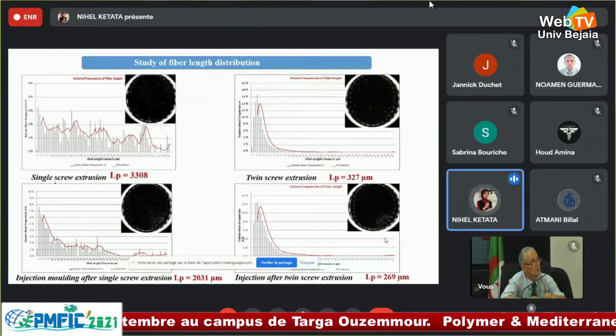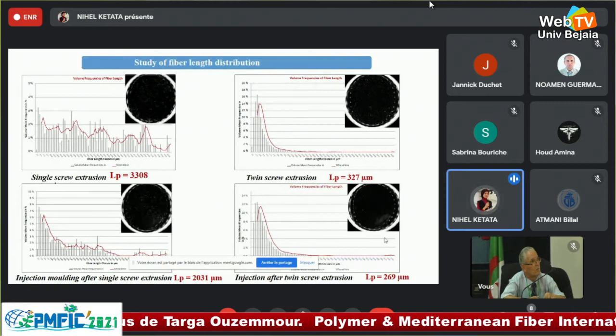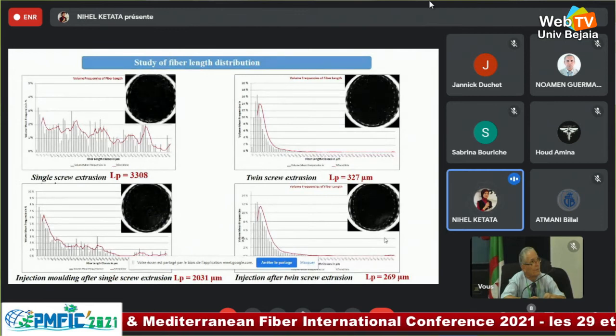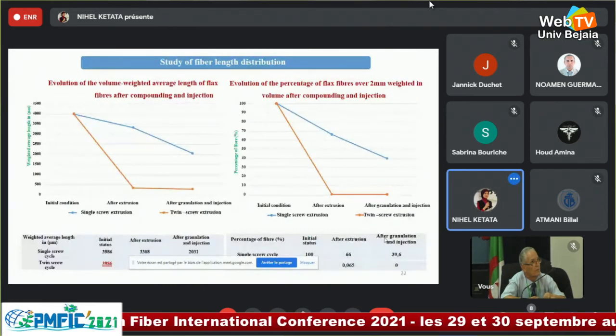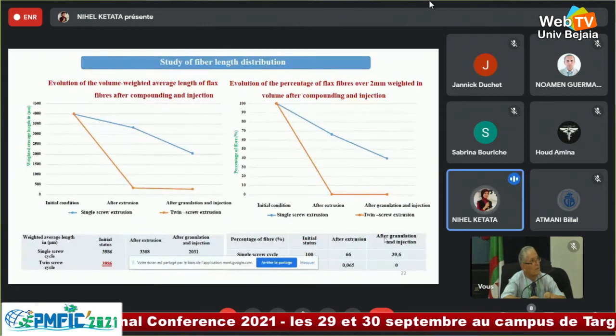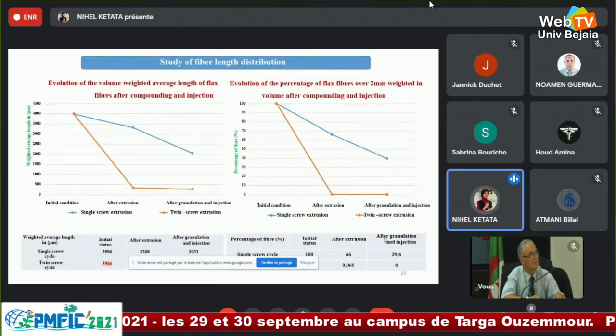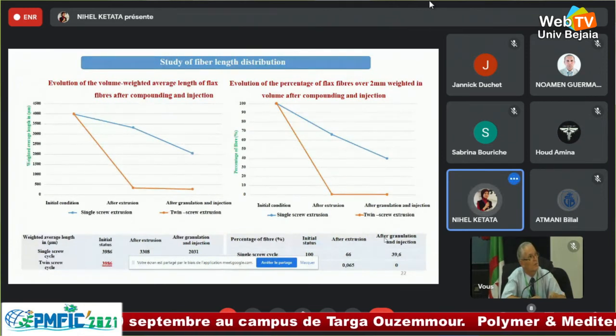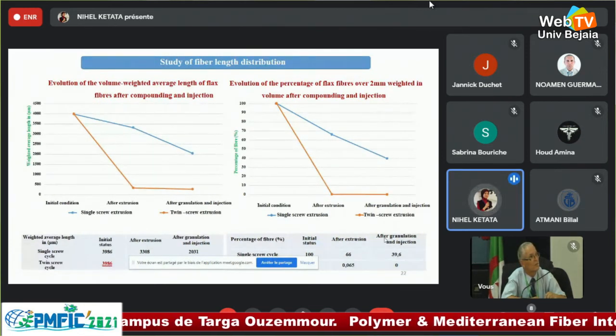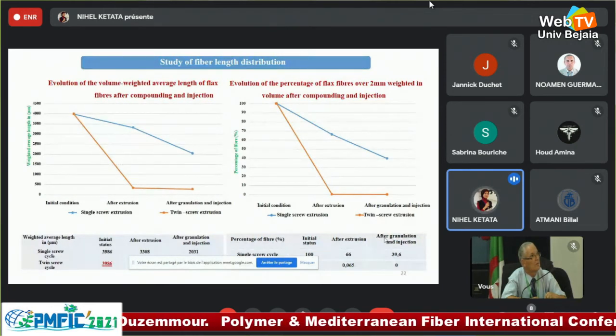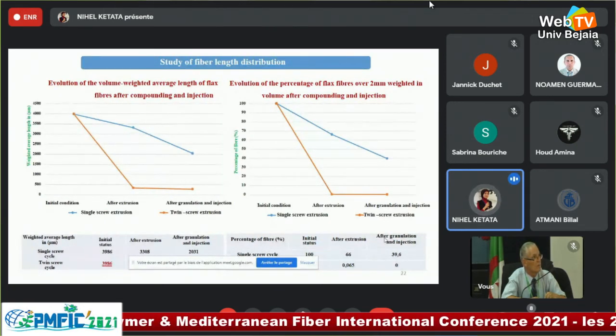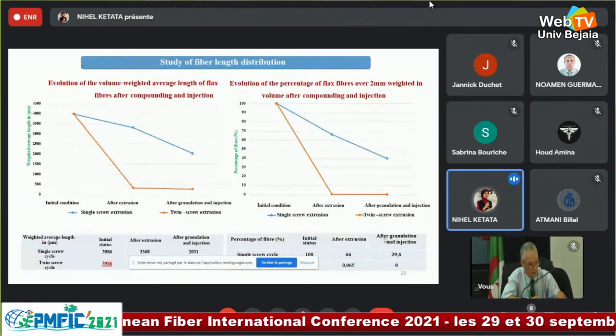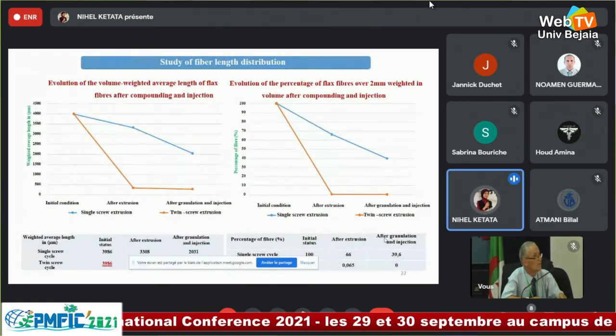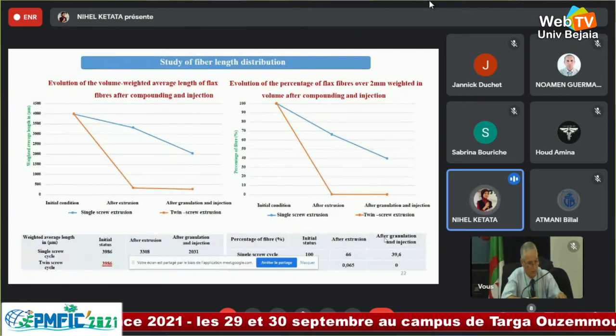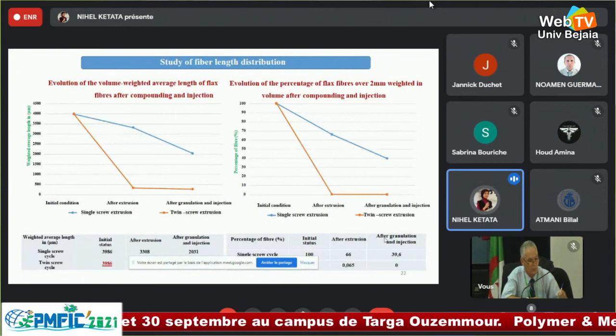So the four processes give us a different length of the fibers. We work on the observations of the fibers obtained by the scanner for the four processes. These studies show a reduction in the average length of the fibers from 4 millimeters to 269 micrometers after the injection of the pellets obtained in the twin-screw extrusion. This effect was mainly associated with the compounding operation and not with the injection operation.